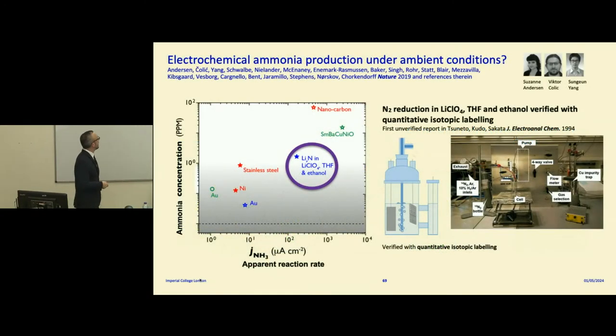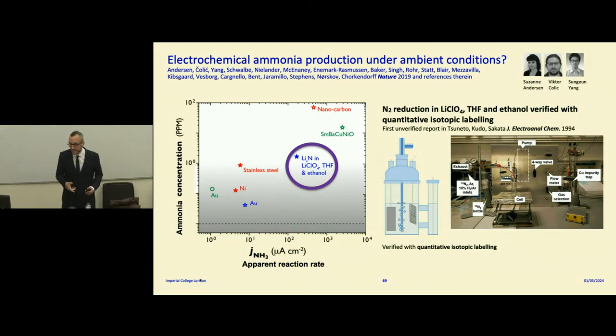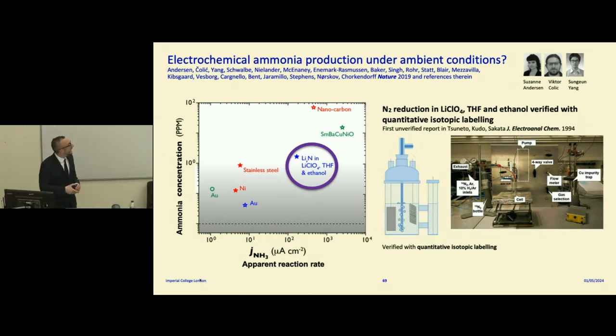So in my old research group, we looked for years and years to try and make ammonia using electrochemistry, and we failed really miserably for many years. But lots of reports in the literature started saying they could do it. So we set up a protocol saying, if we were to make ammonia, this is how we prove it. And what we found is that a lot of the reports in the literature were reporting such small amounts of ammonia that what they were actually looking at was contamination from the lab environment. So it was actually all nonsense, in fact.